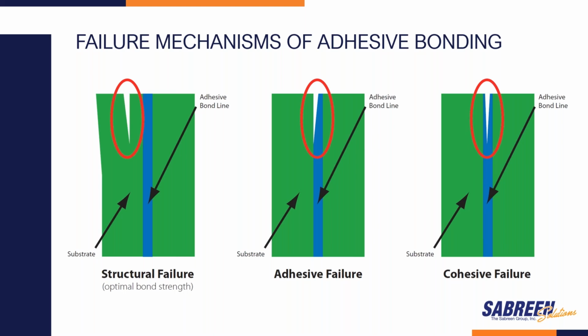This is the highest level of bonding that can be achieved, the optimal bond strength, and this is where the material, the polymer, cracks within itself, indicating that the adhesive bond that we're using is even stronger than the material. And for inks and coatings, we strive to achieve zero removal of the coating, the paint, from the base material, as would be tested by ASTM standards.